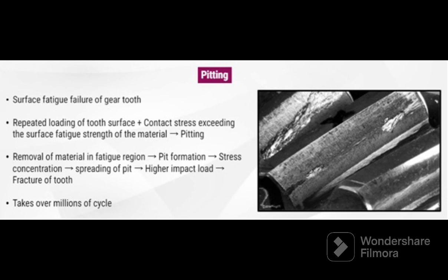What is pitting? Pitting is a surface fatigue failure of gear tooth. It occurs due to repeated loading of tooth surface and the contact stress exceeding the surface fatigue strength of the material. Material in fatigue region gets removed and a pit is formed. Pit itself will cause stress concentration and soon the pitting spreads to adjacent region. Subsequently, higher impact load resulting from pitting may cause fracture of already weakened tooth. However, failure process takes place over millions of cycles.